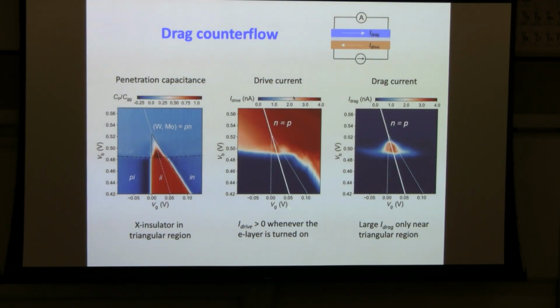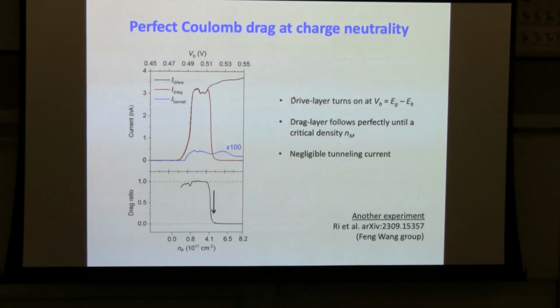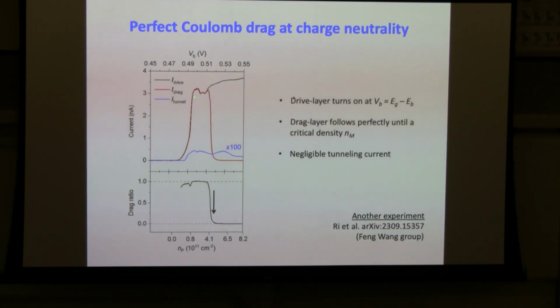So we can make a line cut along the line of n equal to p, meaning that there's complete charge neutrality in the system. And we can look at how the drive current and the drag current scale with the pair density in the system. So this is the result along that charge neutrality line. The black curve here is the drive current. It gets sharply turned on once the electron channel is doped by electrons. The red curve here is the drag current, which is the current that spontaneously flows in the hole layer. You can see that once it's turned on, it follows the drive current nearly perfectly until some critical density, which I will come back to later. At this critical density, it sharply drops to 0 drag current.